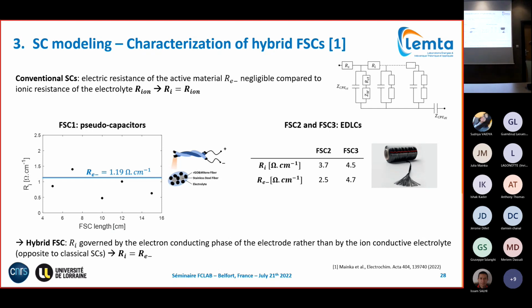And we tested this as well on the fitting of pure capacitive fiber-shaped supercapacitors, where the active material is pure carbon. I did not show you the fitting data. Conclusions are the same as what I showed you before. So here you have the devices, and just know that here we have pure electrical double layer charge storage, without contribution, or very slow contribution still. And here again, the internal resistance we identified was very close to the electric resistance of this carbon. So again, it seems that this fiber-shaped geometry is at the origin of this internal resistance. So this was the major finding of our model.